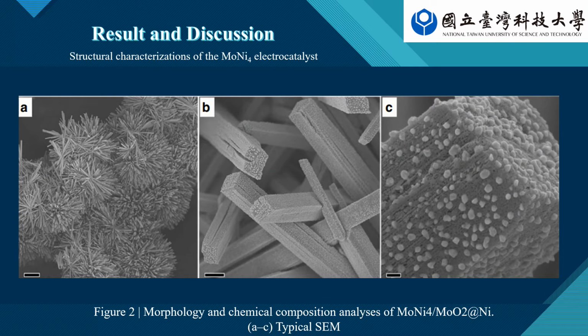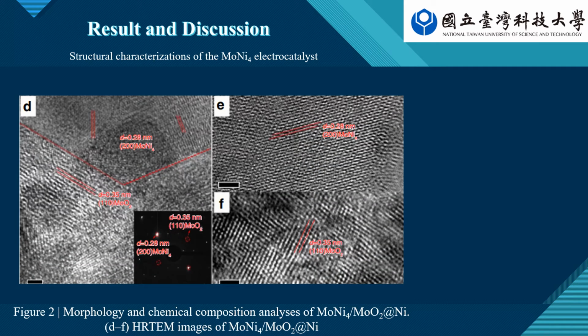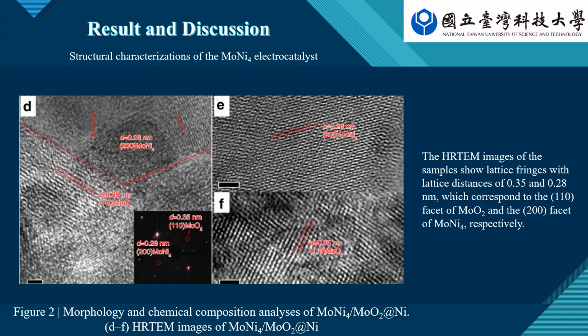As shown in figure 2A, B, and C, numerous nanoparticles with sizes in the range of 20 to 100 nanometers are uniformly anchored on the cuboids, which are vertically aligned on the nickel foam. Clearly, the high-resolution TEM image of the sample shows lattice fringes with lattice distances of 0.35 and 0.28 nanometers, which correspond to the 110 facet of MoO2 and the 200 facet of MoNi4 respectively. The selected area electron diffraction pattern shows the diffraction pattern of the 200 facet of MoNi4 and the 110 facet of MoO2, as inserted in this figure.